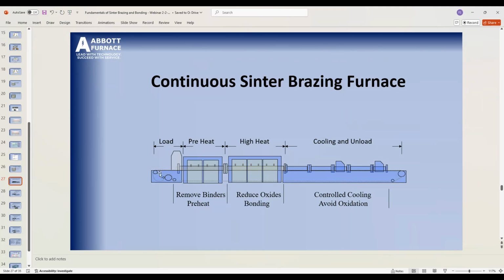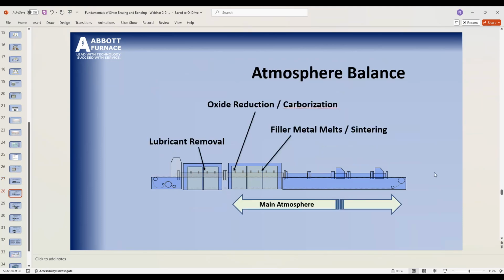And so I have a schematic here of our furnace, and we have our load and our preheat, our high heat, and our cooling section, right? And if we look at this in the preheat, the first 2/3 of that preheat's where we remove all the lubricants from the compact. And then as we go from the 2/3 of the way into the preheat to about the beginning of our high heat, that's where we're going to reduce our oxides. But that's also where we're going to hit that 1850 mark, our 1010 degrees Celsius. That's where we're going to start to carburize that surface to keep the base metal from stealing the filler metal. Then we're going to melt.